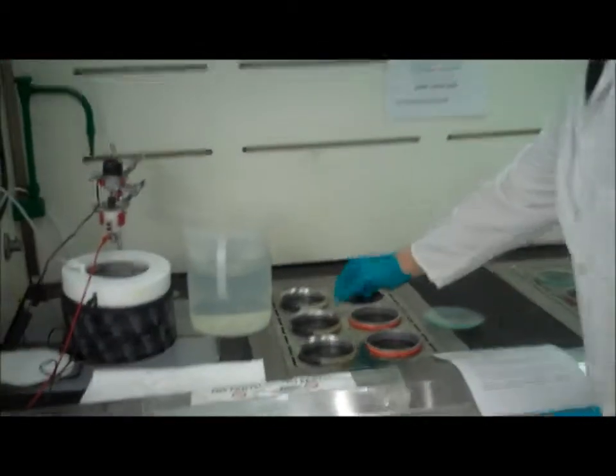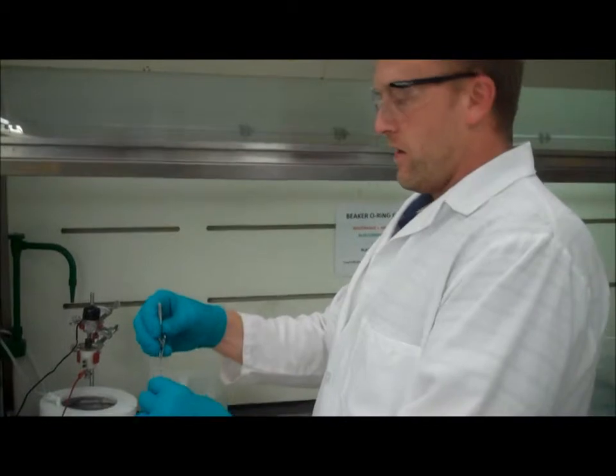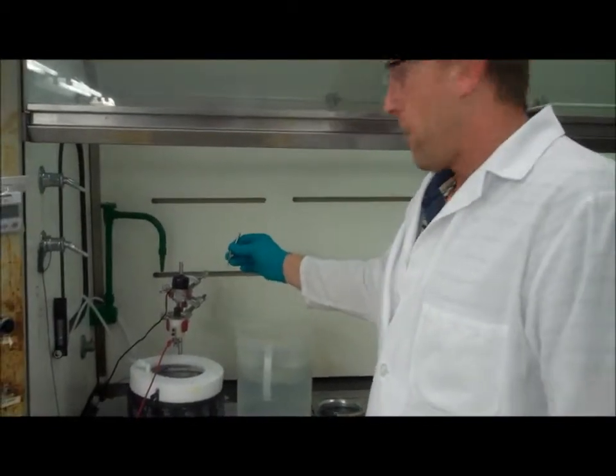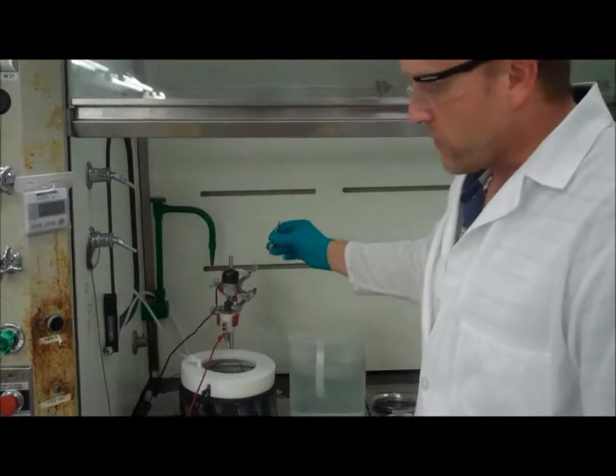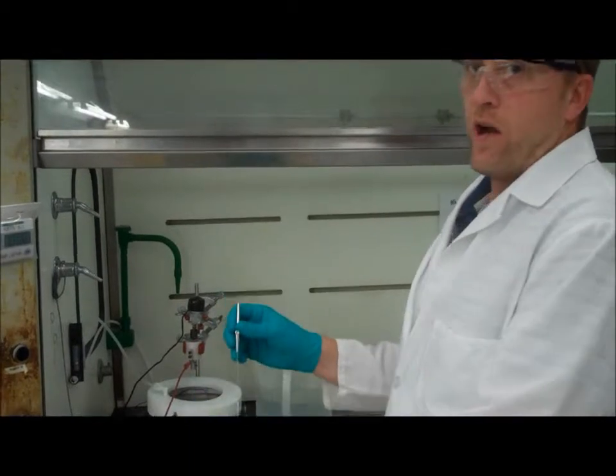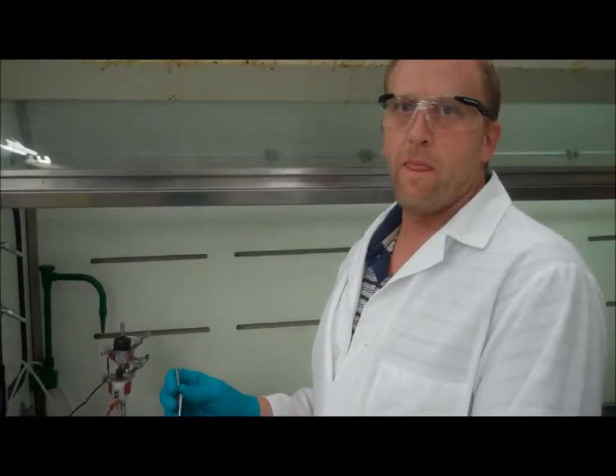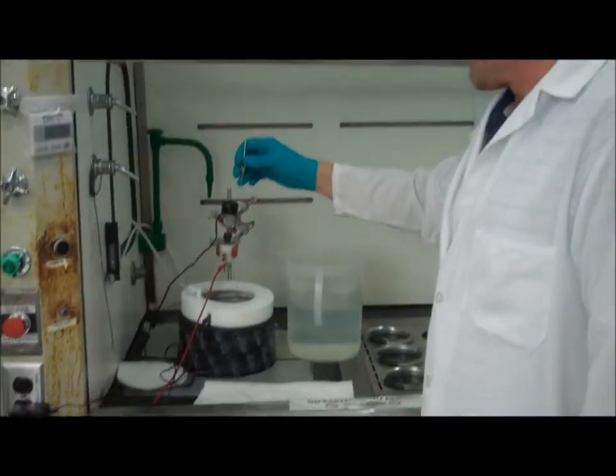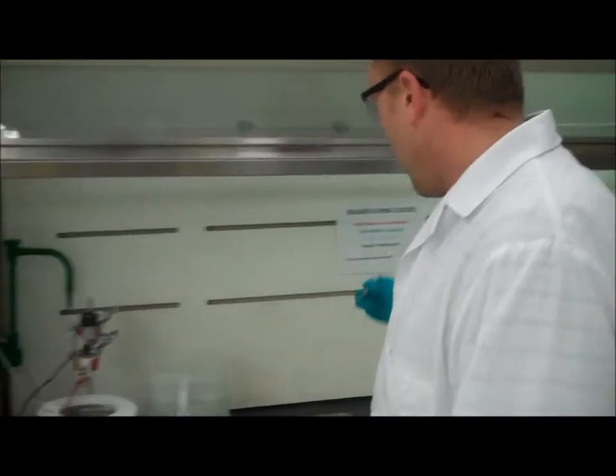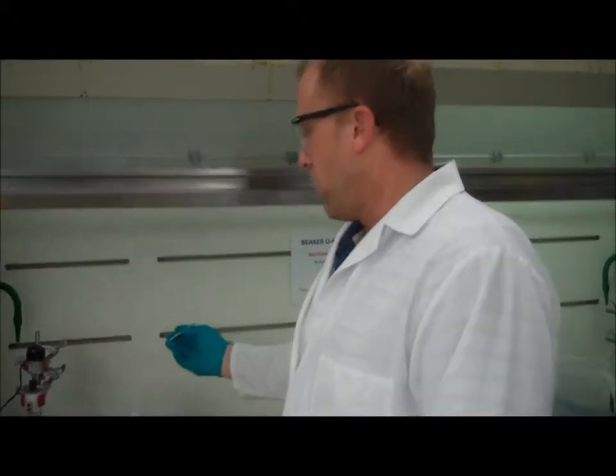What happens is you take your wire with your part on it, you attach it to a clip, and then you fix it to the anode. Now we've done a lot of investigation on what kind of current densities, what kind of voltages, how much current we actually want to run through this wire, and for how long. So we calculate our total coulombs that we want, and that gets calculated into amp minutes. And so the part will get processed, it'll get polished, then it gets cleaned, then we measure it to make sure we hit our target diameters. Inspect it to make sure that there are no abnormalities that could cause a problem in the future.